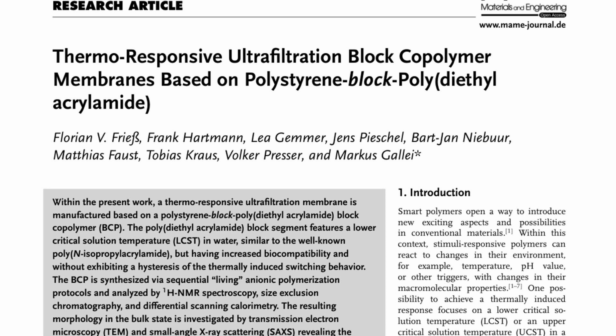The authors first synthesize the PS-b-PDEAAm block copolymer using sequential, living, anionic polymerization protocols. The resulting copolymer is characterized using various techniques such as 1H-NMR spectroscopy, size exclusion chromatography, and differential scanning calorimetry. The morphology of the copolymer in the bulk state is investigated using transmission electron microscopy (TEM) and small-angle X-ray scattering (SAXS), revealing a hexagonal cylindrical morphology.